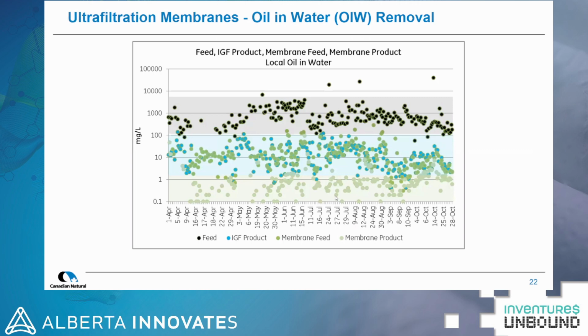Here's the combined data set for oil in water removal for the ultrafiltration membranes. The upper band with the black dots is the feed into the IGF. And then the middle band is the treated water out of the IGF. And the lower band is the water quality coming out of the membranes. You have to graph this logarithmically because there's orders of magnitude drop in oil concentration as you move from one step to the other. What's shown in the lower band, the upper end is 5 ppm, which was our target for the treated water out of the membrane.